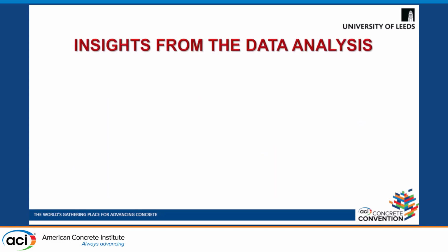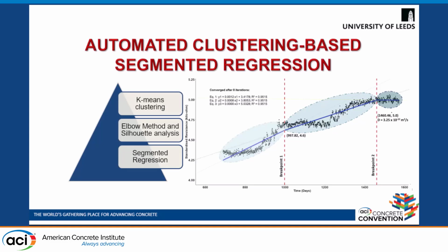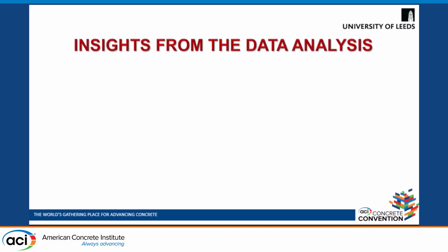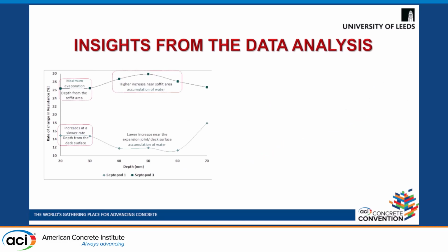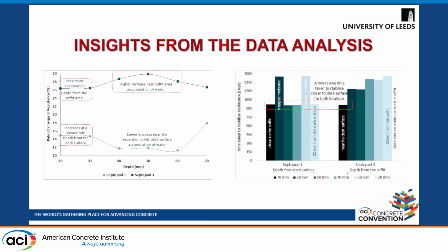So this approach was used on all depths for both the sensors, and the insights obtained from the data analysis are that the resistance was continuously increasing. However, there was a slow increase near the depth of the deck surface, while there was a faster rate of change and increase near the soffit area because of the maximum evaporation happening there, because of the presence of breathable coating at the soffit. Secondly, it took more time to stabilize near the soffit, and it took almost the same time to stabilize near the deck surface at both the locations.